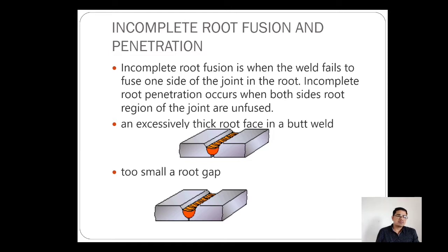So friends, if you remember, in the last class we discussed root face, root gap and many terminologies. If the root face, which is on the root side, is higher in thickness, then during welding the root face may not melt. When the root face does not melt, the liquid weld metal may not completely penetrate. So that may be one of the reasons for lack of penetration. And second, too small a root gap. Root gap normally, friends, we take like the diameter of the electrode, and when we take the root gap low, then the weld may not properly penetrate the root.